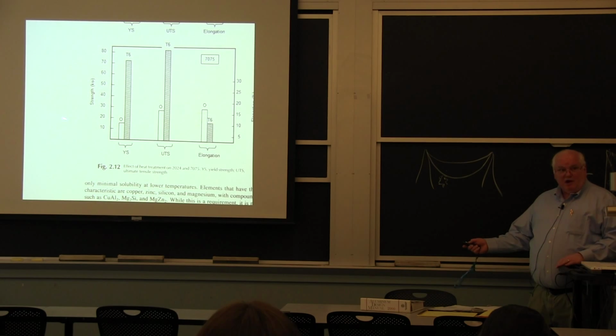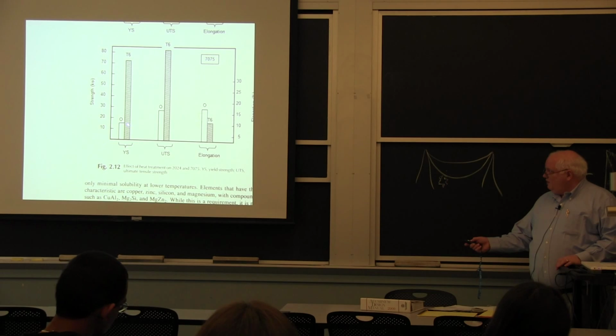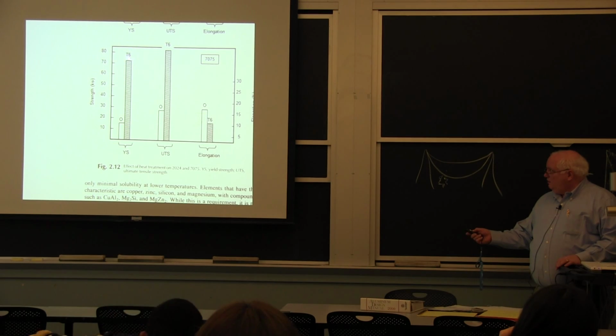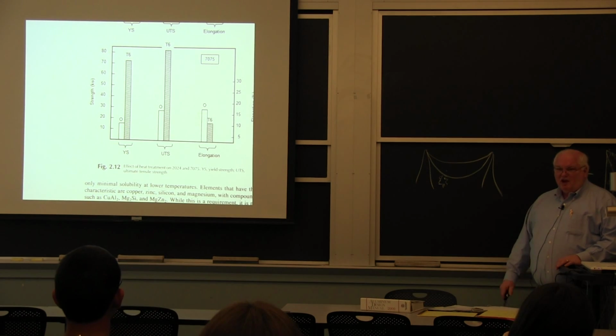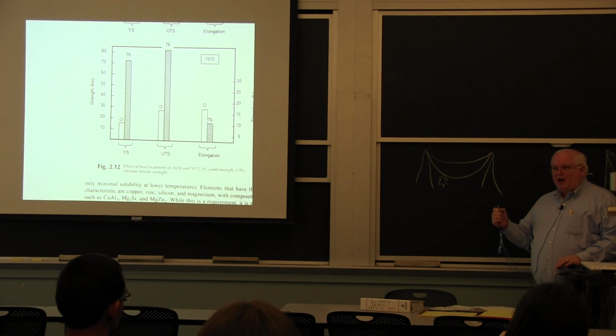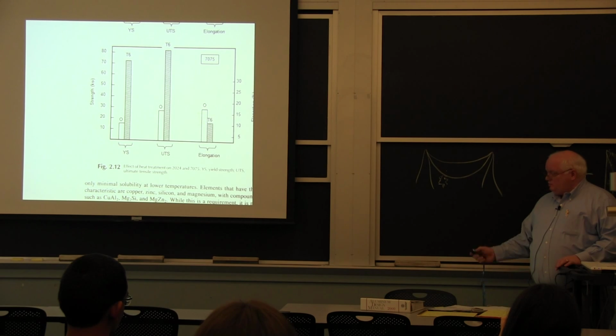This is 7075. Again, big increases from 16 ksi annealed, T6 condition, 75 ksi. Not as strong as an aluminum baseball bat, which could be 100 ksi, but still pretty good. And here's the elongation. When we start getting these types of strengths, we do start losing some elongation in some of these alloys.